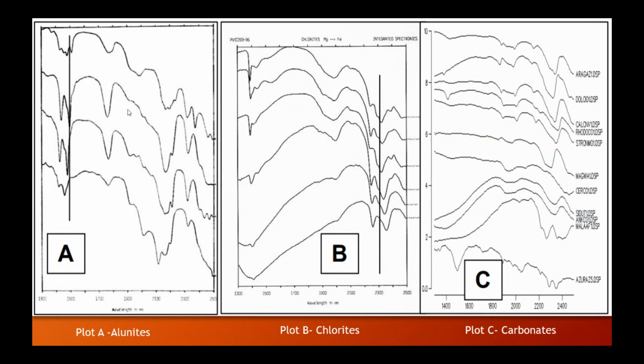So the spectral plots in A are for alunites of different compositions, starting at the top from calcium to sodium to potassium to NH4. Note that the diagnostic feature ranged from 1495 nanometers for calcium to 1460 nanometers for NH4. In plot B, the diagnostic wavelength occurs in the 2330 nanometer range for magnesium chlorites, shifting to 2350 nanometers for iron chlorites. The carbonates group are in plot C, and these minerals show a significant shift with different cation compositions, ranging from top to bottom. So the very top being aragonite, the very bottom being azurite.